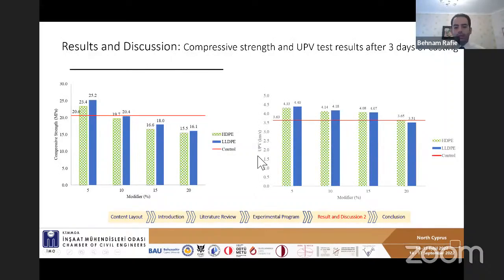In compressive strength and UPV test, we found that our control sample or specimen got 20 megapascal in 3 days, and adding 5% of modifiers, each modifier, high density polyethylene and linear low density polyethylene, we increased the compressive strength, and by adding 10%, it's almost the same, but adding more than this amount, we didn't have any improvement because during the mixing, we may have some balling problems by adding more polymers. UPV test also confirms that adding 5 and 10%, the velocity of the pulses are increased, and it's obvious.